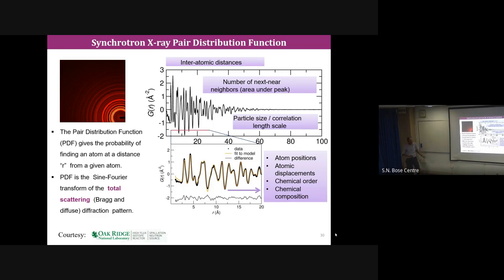So basically, this technique can not only tell the global structure of a compound, but also the local structure. So it is a very powerful technique. But normal crystallography, like single crystal diffraction or powder diffraction, you only get the global structure. You don't get local information. That averages out, and you only get the global structure. But with this technique, you can get local as well as global structure. So that's what we try to probe.